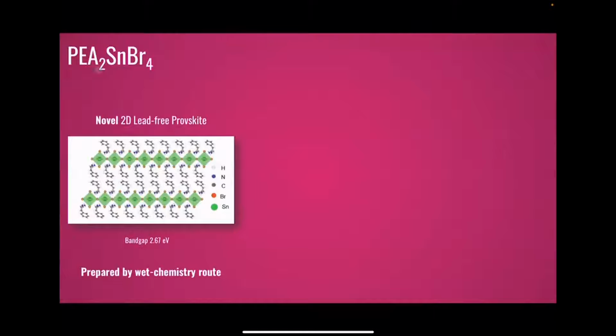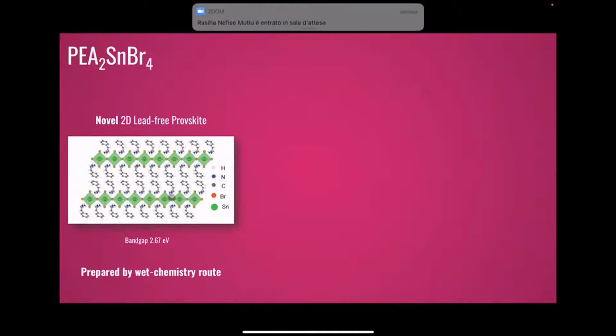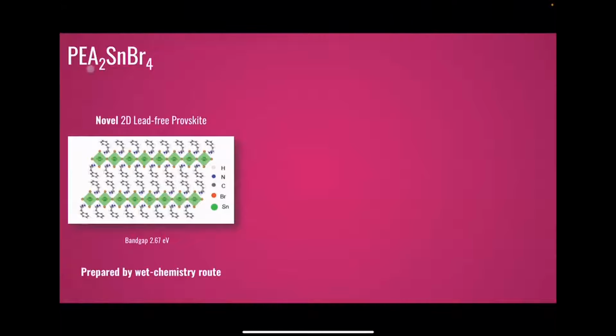So one of the first systems we investigated is this one. PEA means phenylethylammonium. Here you see the crystal structure. So it's phenylethylammonium 2 tin tribromide. So you see the structure, you have a layer of octahedra. Okay, this is a Ruddlesden-Popper perovskite. You have one single layer of tin bromide 6 octahedra separated by two phenylethylammonium cations. So you still keep the properties of the inorganic framework, tin tribromide, which dominates the electronic properties in terms of band gap and absorption, but then you have these organic spacers that improve, for example, water stability.